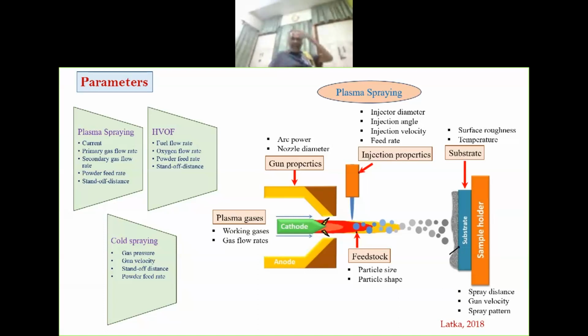Look at it closely. You take, for example, the feedstock particle. What's the particle size? 5 micron or 50? What's the shape? Is it angular or round? Is it a hollow sphere or a solid sphere? Is it an agglomerated powder or a solid powder? Okay. What kind of arc power are you using? 50 kilowatt or 100? Nozzle diameter, how much is it? 5 millimeter or 10 millimeter?